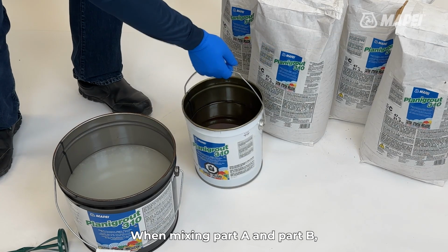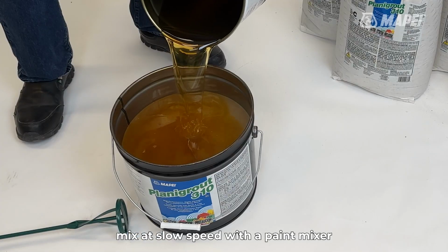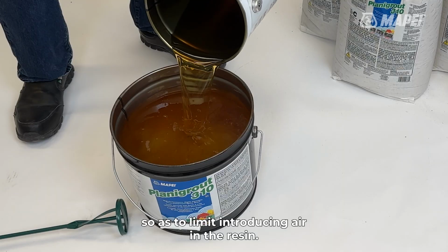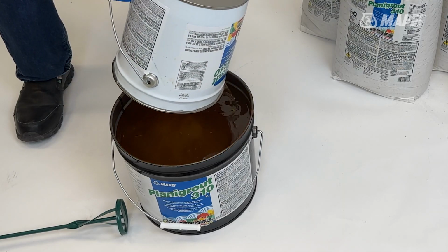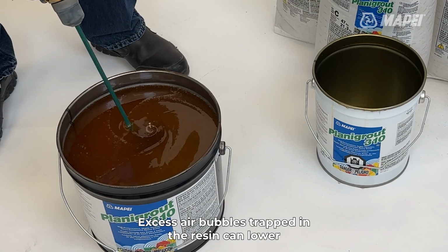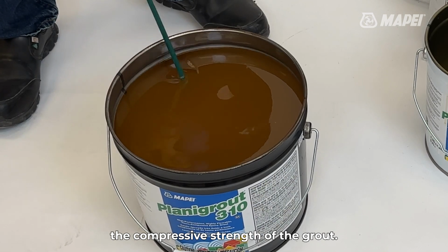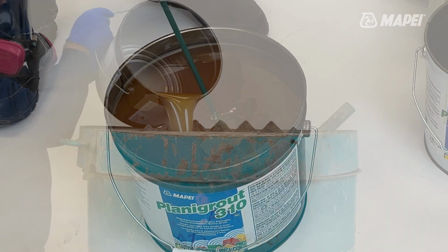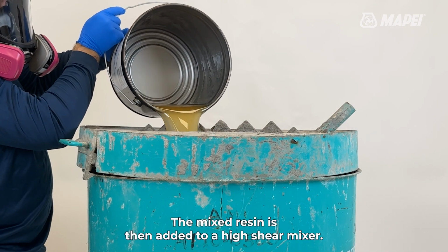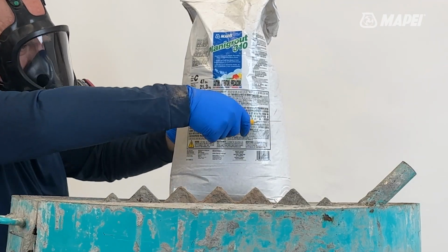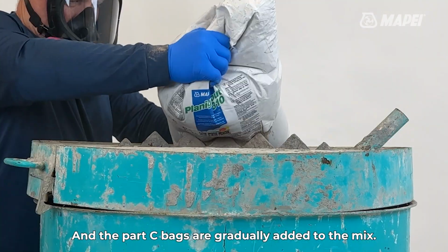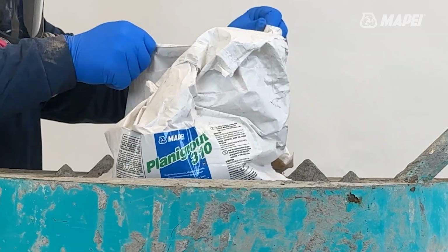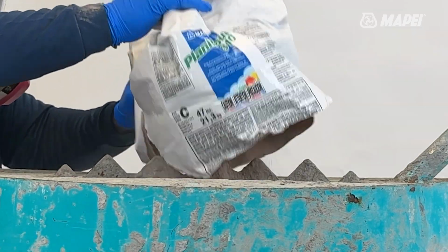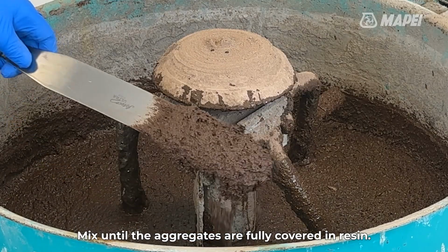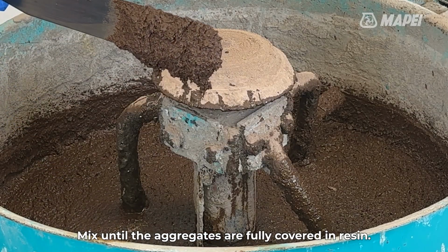When mixing Part A and Part B, mix at slow speed with a paint mixer, so as to limit introducing air in the resin. Excess air bubbles trapped in the resin can lower the compressive strength of the grout. The mixed resin is then added to a high shear mixer, and the Part C bags are gradually added to the mix. Mix until the aggregates are fully covered in resin.